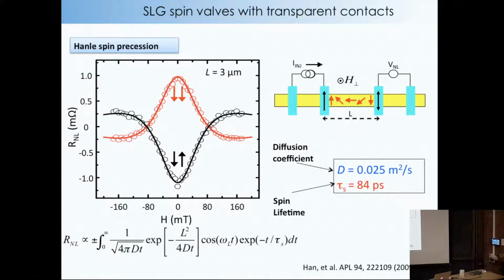And so in the first works that came out by Van Wees, all the lifetimes were like 100 picoseconds. I think 150 was the highest. And we see, okay, it's like 80, 84, okay? And so one question is, why is this so short? Because it should be long. Theoretically, it should be like maybe a microsecond. And this is much, like orders of magnitude shorter. And so this is still one of the mysteries of the field.